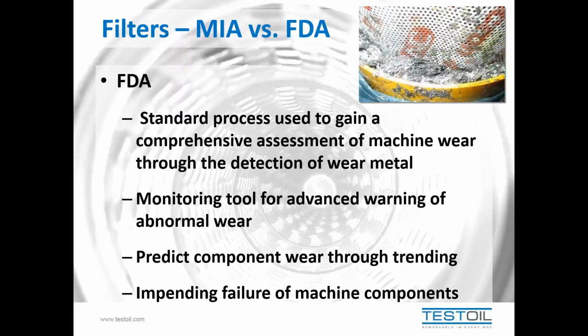So really, when we talk about filter debris analysis, we're trying to gain a comprehensive assessment of the machine wear that may be occurring in the system. And it can help us provide advanced warning of abnormal wear and critical operation through trending. And we can predict component wear in our critical rotating equipment through trending of this type of testing, and hopefully identify any impending failure of machine components. And really, this test is geared towards detecting wear metals. So we're looking for if there's an issue with potentially damaged bearing, metal piping corrosion, or if a pump is wearing.